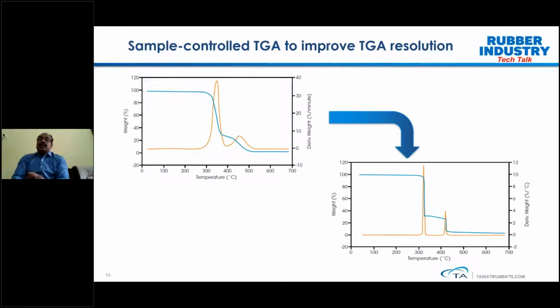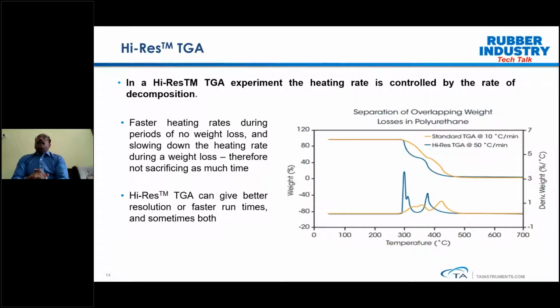So that is what you see here, how the decomposition pattern is resolved in a better manner, and your derivative peaks look very, very sharp. That is the advantage of your high resolution TGA. Here you can see an example for the polyurethane samples. Just for the information, we took a polyurethane. If you see the decomposition, the standard heating, the orange curve, is running at 10 degrees centigrade per minute. The high resolution TGA is starting at 50 degrees centigrade per minute.